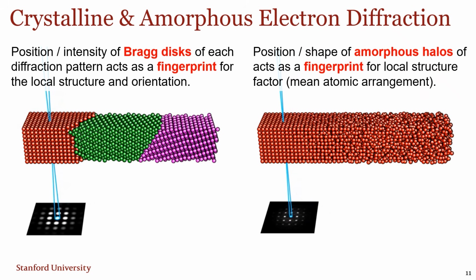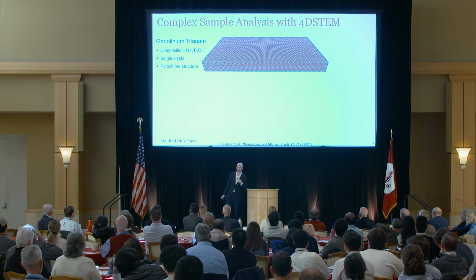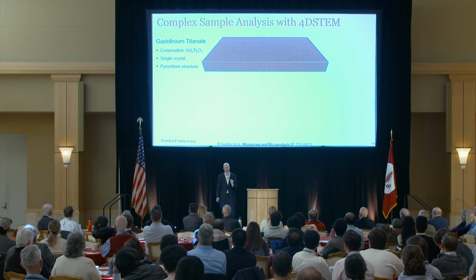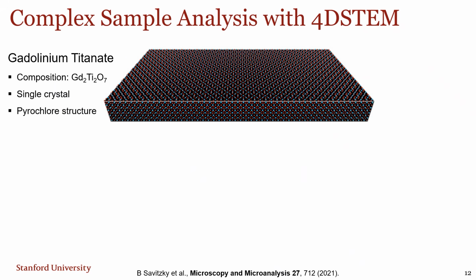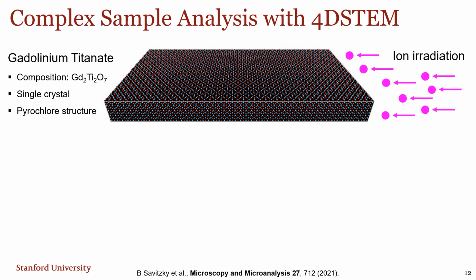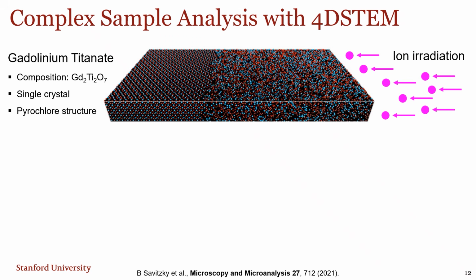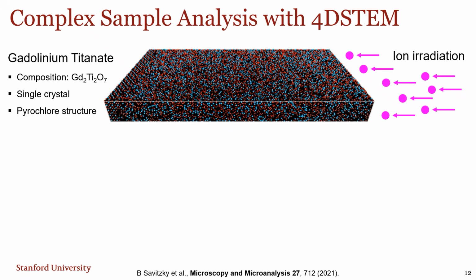So you can imagine that we can use computer algorithms to identify these different structures and invert or infer what the sample looked like here. So let me show you a real experimental data set. This is gadolinium titanate. It's a material that was being studied by Los Alamos for fusion reactor cladding materials, actually. And so what they did to study the resistance against ion irradiation is they put it in the reactor, and what this causes is amorphization of the material. Deep, deep, deep down into the sample, you're randomly displacing all the atoms and removing that crystalline order structure.